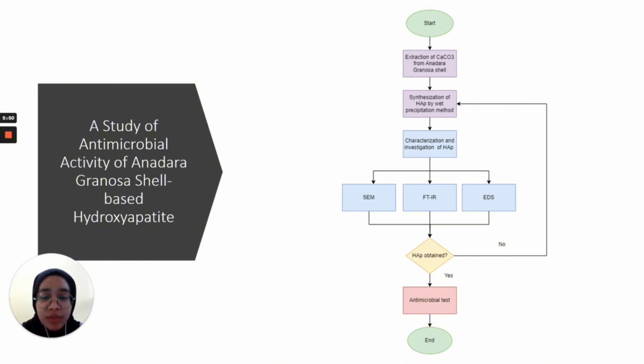And then we can proceed with the antimicrobial test by using the agar diffusion method. In this test, we employ S. aureus and E. coli as the gram-positive and gram-negative bacteria. In this study, we use the antibiotic amoxicillin as the positive control and distilled water as the negative control. The plates are incubated at a temperature of 37 degrees Celsius for 16 hours.